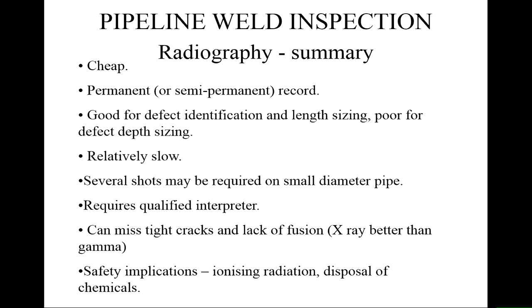So if you imagine, if you've got a big open space, the X-rays are coming through, there's no absorption in that big open space, that will give you a difference in intensity. If the crack is very narrow, it only has a small path through the open space, there's very little detectable difference in intensity under those cases. So going across a crack, you don't see much. Going along the length of the crack, you tend to see more intensity. So you've got to be very careful about which orientation the material is.